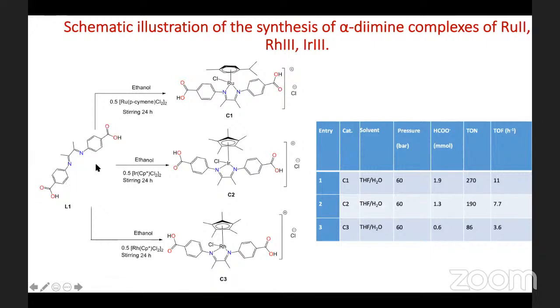Of course, she tested all the ligands that I have shown you here, and then we produced these ruthenium, iridium, and rhodium complexes. As you can see here, again, our carboxylic acid functionalities are very much free, which then allows us to synthesize metal-organic frameworks containing catalytically active ruthenium, iridium, or rhodium complexes. But of course, before we proceeded to do that, we tested these complexes to see if they are active towards the hydrogenation of carbon dioxide to form formate.